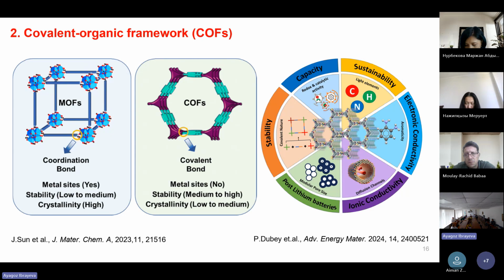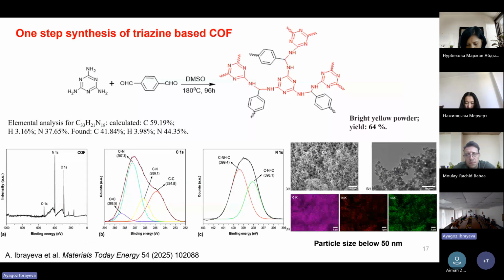And for this, we synthesized it by Schiff base reaction, through melamine and terephthalaldehyde in the presence of DMSO for 96 hours at 180 degrees, and we obtained bright yellow powder with a yield of 64%. To know the local oxidation state of this material, we provided XPS and deconvoluted, and we can see the formation of these covalent bondings. The morphology was done at the same time as this analysis.